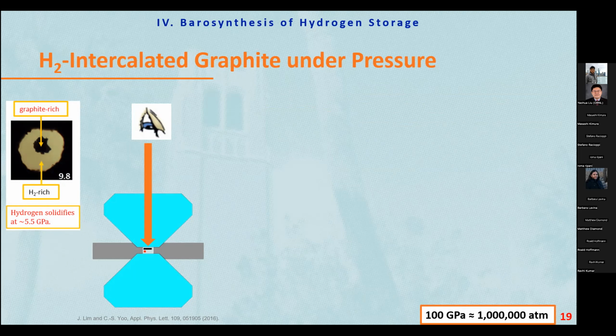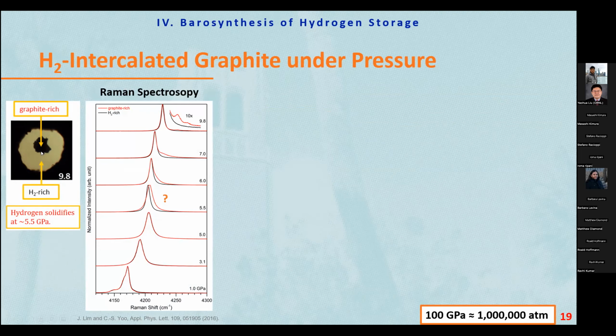You can measure on the microscope. It's 1 micron thick graphite, and there's a ruby, and the pressure medium is hydrogen itself, surrounding the graphite. And now you are seeing it from the upper diamond. This is the picture. And you can do Raman spectroscopy with this, probing the different regions, the hydrogen rich region and graphite rich region. If hydrogen is in the same condition, there should be no difference between these regions. But above 5.5 GPa, we see the difference.